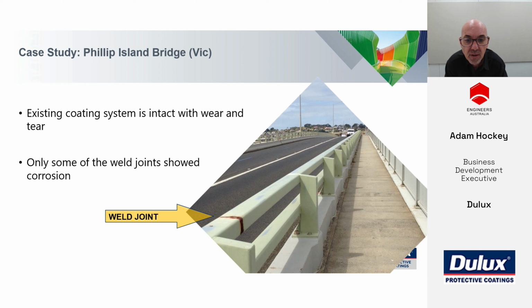That is a good example of site repairs on weld joints when they're not done to conform with the original system. So you can see the original system is all intact and in place, and we've got a band of corrosion where there's been some welding done, where the coating system wasn't installed or applied the same as it was for the rest of that guardrail. This is quite common when we're talking about weld repairs or site repairs of newly installed steel. If we don't provide the specified coating system and we just do an on-site quick repair, that area will break down whilst the rest of the system will stay intact.